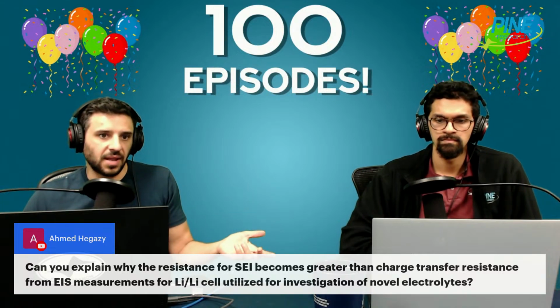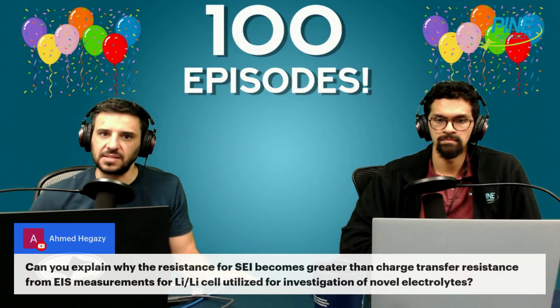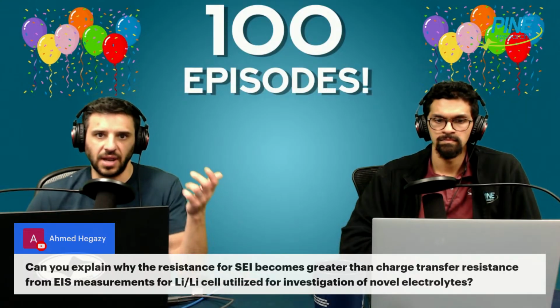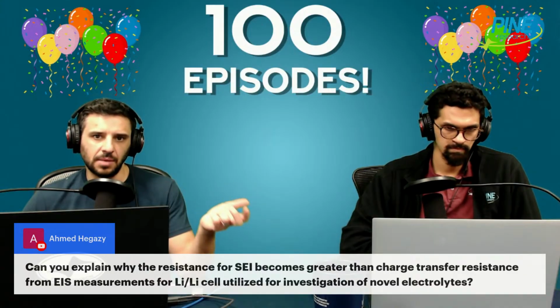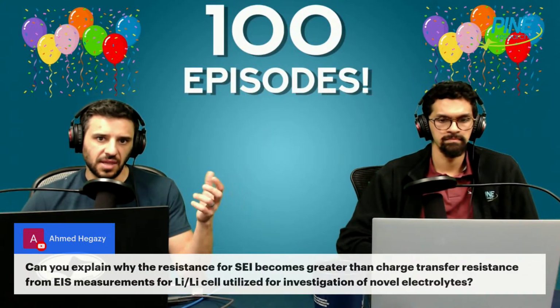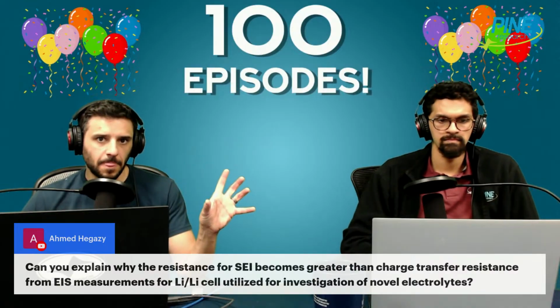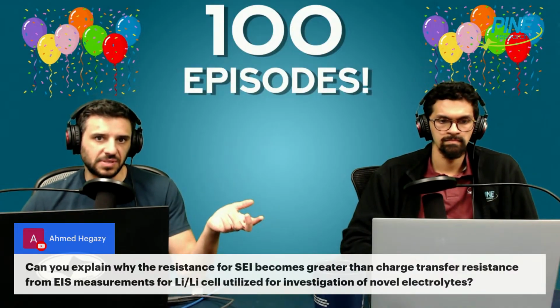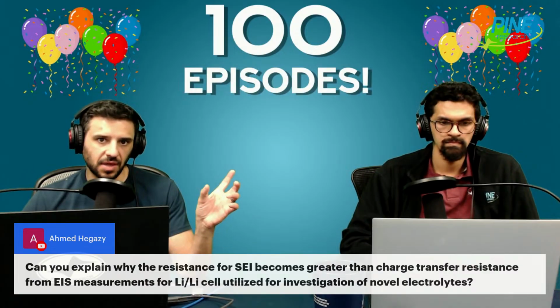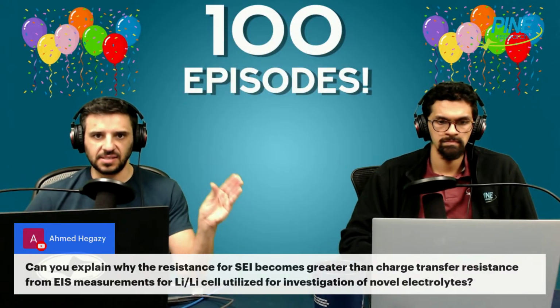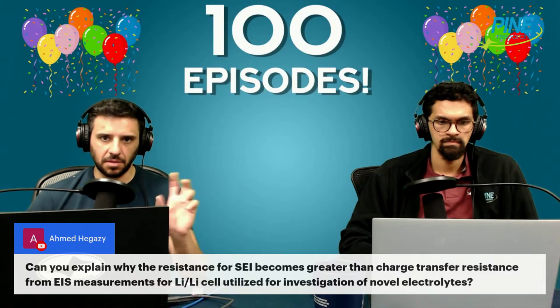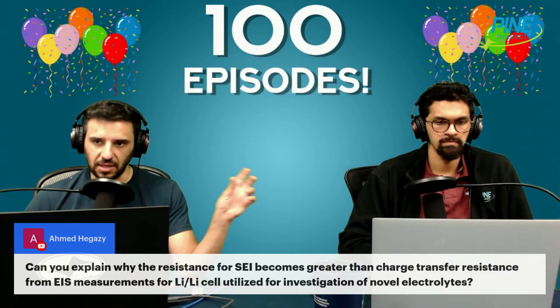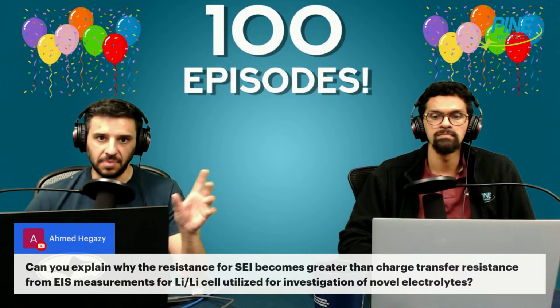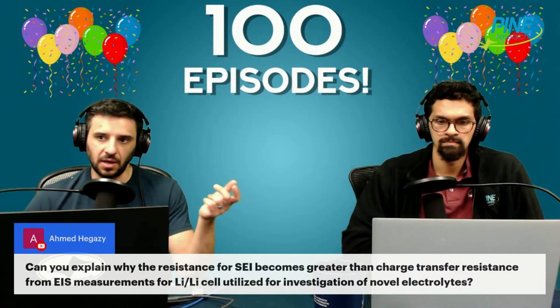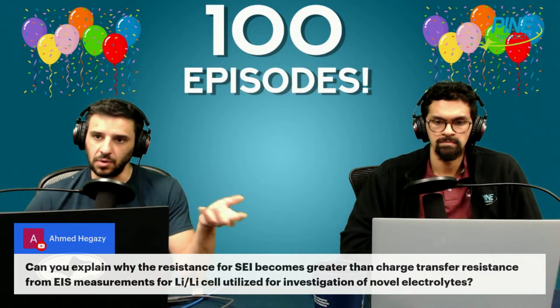Now, this sounds great. Oh, I get extra charge capacity. It sounds kind of good, but it's not, because it's not really stable, and it's not the mechanism you're trying to study, and it's not necessarily repeatable or predictable. It can also lead to the SEI becoming thicker, possibly collapsing. If the SEI grows and becomes too thick and isn't in a stable thickness and state throughout charging and discharging, it can collapse or become really thick, and if it collapses, the whole battery can die or go into thermal runaway.